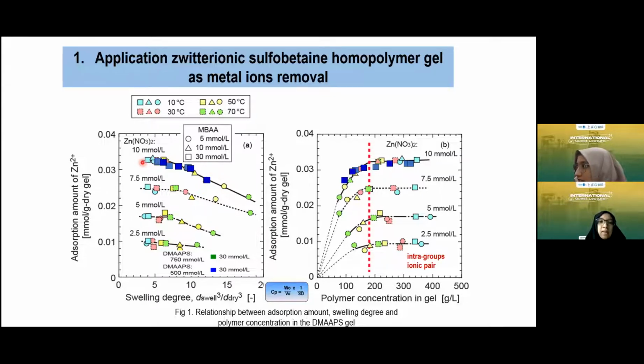As we can see, an interesting correlation can be seen because the data points fall on the same line regardless of crosslinker concentration, temperature, or the concentration of the solutions. As we can see, with increasing zinc nitrate concentration, the adsorption amount also increases. At lower swelling degree, up to 5, it remains unchanged and decreases gradually with increasing swelling degree, from 5 up to 15.